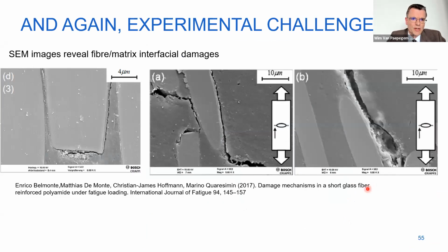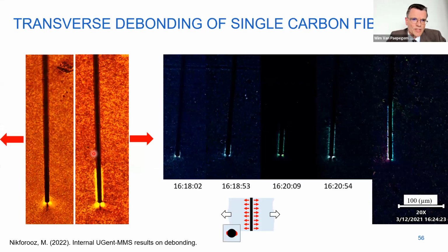And a second experimental challenge is definitely interfacial characteristics. So Marino Quaresimin's group showed already in the past with SEM images that in the interface, there is also happening a lot in short fiber. And there we try to isolate this phenomenon and have it observed in real time. So here you see some measurements where we have a single short fiber. So this is about 7 microns. And we can observe in transverse loading, because most interfacial tests are in shear, but this is in transverse loading. We can over time see the progressive debonding of a single fiber. And this way try to understand how these debonding mechanisms work.